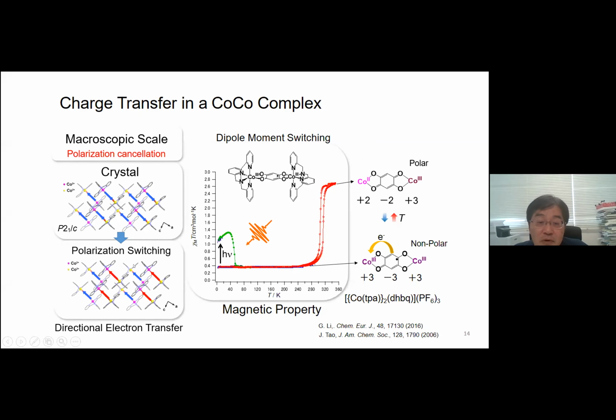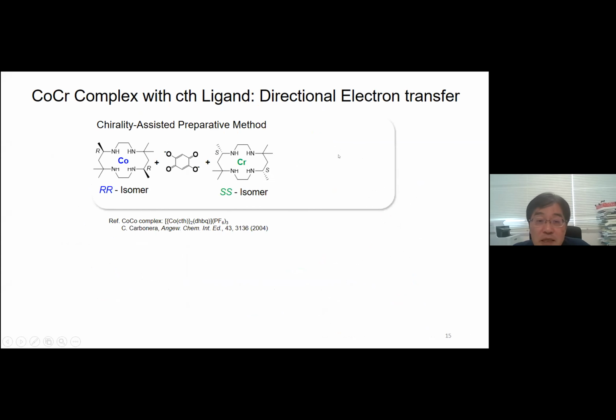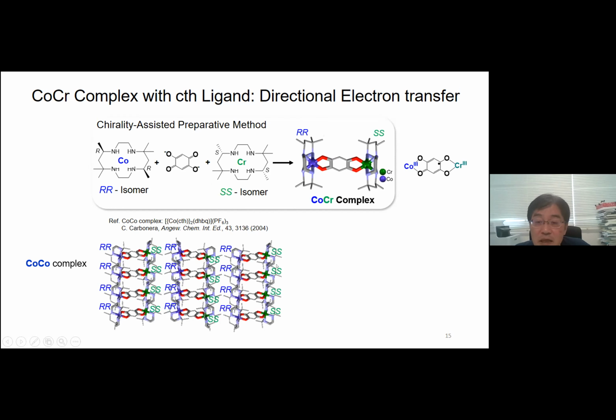So to realize polarization switching using electron transfer, we designed heterometallic cobalt chromium dinuclear complex using chiral ligand. Cobalt complex with RR chirality and chromium complex with SS CTH ligand, and synthesized heterometallic cobalt chromium complex. And the cobalt complex has already been reported, and we analyze single crystal structure. Then these are SS ligand and RR ligand, and this is SS ligand and RR ligand, SSRR, aligned alternately as shown here, and the cobalt is here.